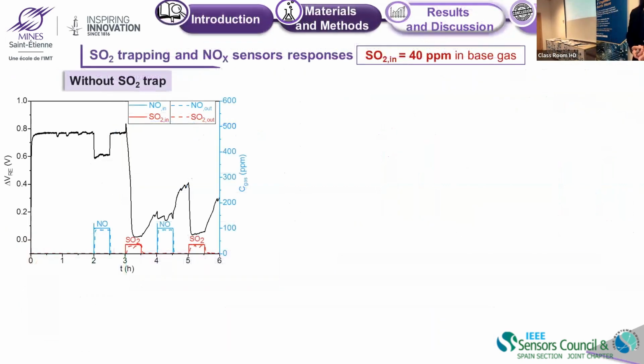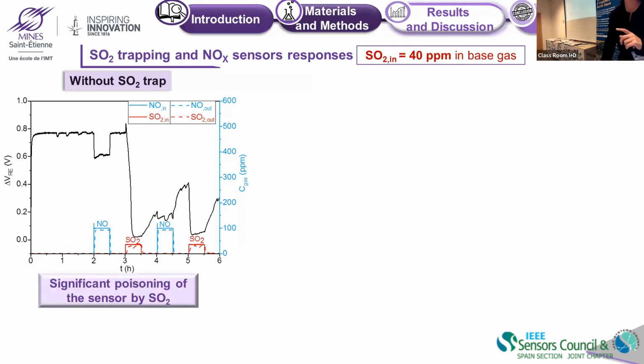So we can continue. Without the trap, you can see here the influence of adding SO2. I already showed you, but before adding SO2, the NO response is a classical one. And as we add SO2, the response is totally disrupted. Even the injection of NO is then not visible and the baseline is totally lost. So there is a significant poisoning of the sensor by SO2. Here it's 40 ppm in the base gas.